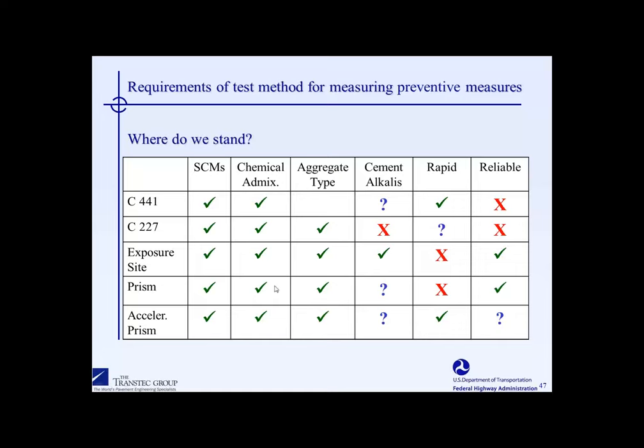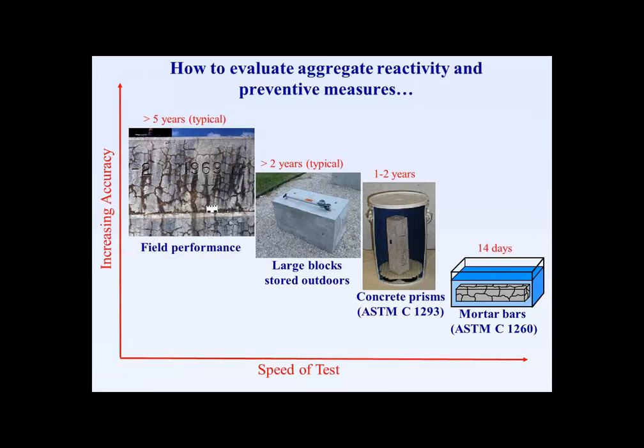The concrete prism test has quite a few positive attributes, but we know we can't evaluate cement alkalis due to leaching, and we know that 1 to 2 years might be too long for many researchers. The accelerated concrete prism test, the test I described where the testing is done at 140 degrees Fahrenheit, has some inherent flaws, and the reliability is the biggest question mark. So hopefully in a few years we'll have a test where we can put a green check in every box, but we're not there yet.